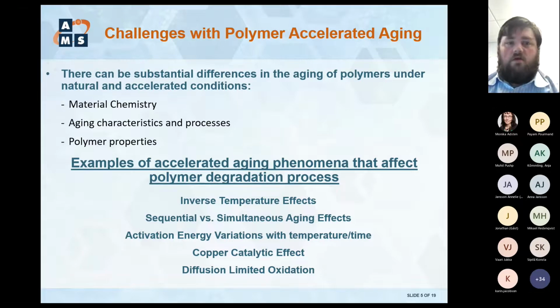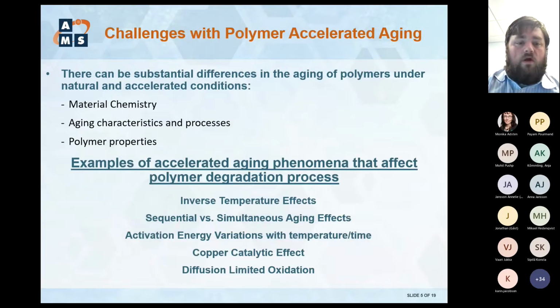And the differences there can be mechanistic. What kind of changes are you inducing in the material and its chemistry and structure? And then depending on what process you use, whether you do radiation, then thermal, or thermal, then radiation, sorry, or if you do any kind of combination, sequential or simultaneous thermal and radiation, what different aging effects are you going to get? Variations in activation energy, obviously, we've shown a little bit, but once you get outside of a certain temperature range, low or high end, during the aging process, oxidation wise, thermal degradation wise, most materials will exhibit differences in activation energies outside of a certain temperature range.